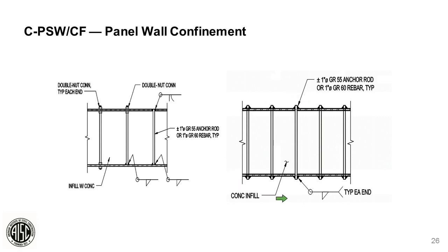In the case of Rainier Square, the fabricator, Supreme Group, chose the option we show on the right, where the rods were not threaded. They were grade 55 rod material, and they were passed through about 3/4 of an inch and were fillet welded on each side. When you space these at 12 inches on center, both vertically and horizontally, you end up with about 240,000 cross ties in the building, which means there are 480,000 welds to make.